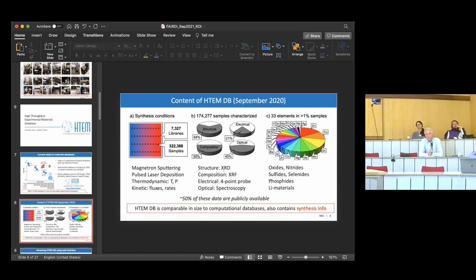Because if you have materials that do not crystallize in the same crystal structure, or even if they do, the properties are often very much determined by grain boundaries or by interfaces. And the exact nature of these interfaces, of course, is something that also is visible for you experimentally. So is this something that you focus on as well, or should that receive more attention?